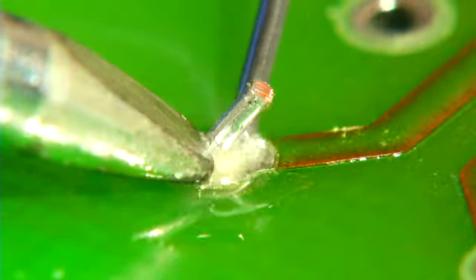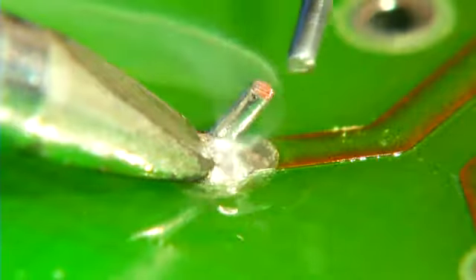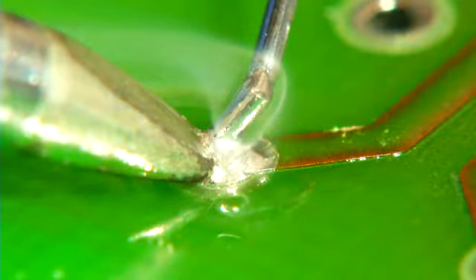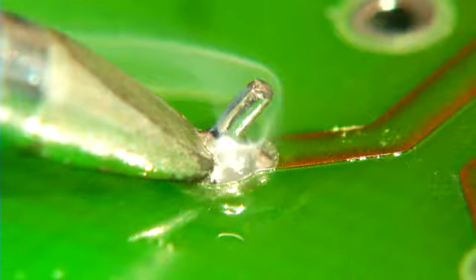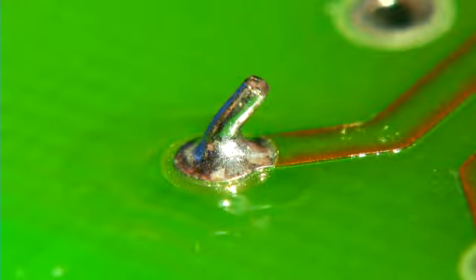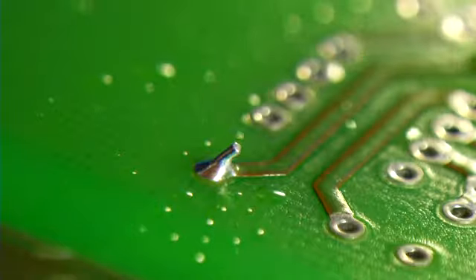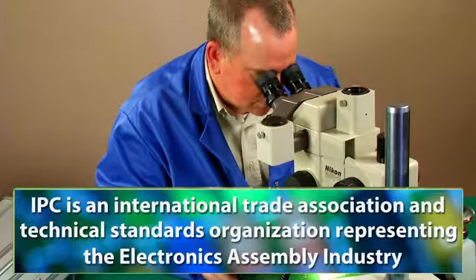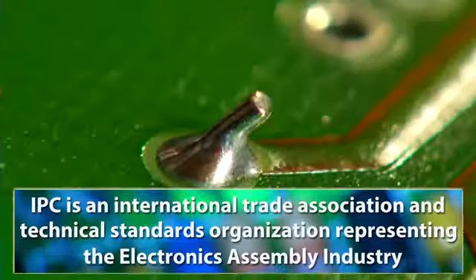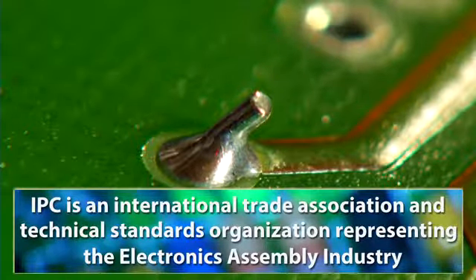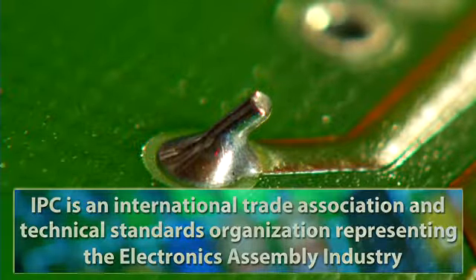Then we'll move the solder wire over to the opposite side of the joint, still touching both the lead and the land. When there's enough solder melted into the connection, touch the solder wire to the tip of the cut lead to cover the exposed basis metal. The solder wire is then removed, followed by the soldering iron tip. At this point, it's important to clean the connection if required. Then, we'll inspect the joint to make sure it looks right. A preferred or target connection is where all of the metals are covered by solder and the outline of the lead remains visible within the solder connection.